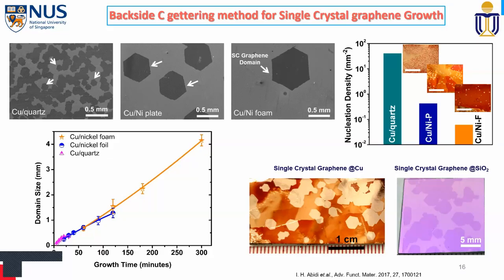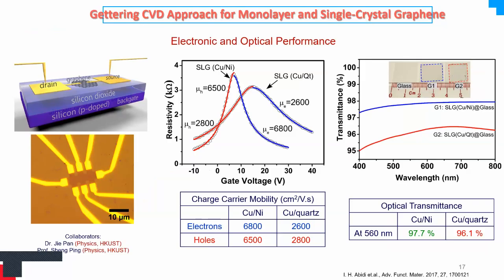At that time, I was able to make one hexagon around 0.6 millimeter. At that time, it was very nice. Now, of course, people have gone beyond that. This kind of growth helped us improve the quality of graphene in terms of electronic properties. Mobility has improved, and also optically, the scattering centers have been removed, so optical properties are a little bit enhanced too.